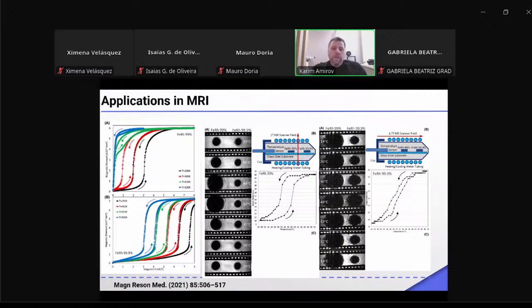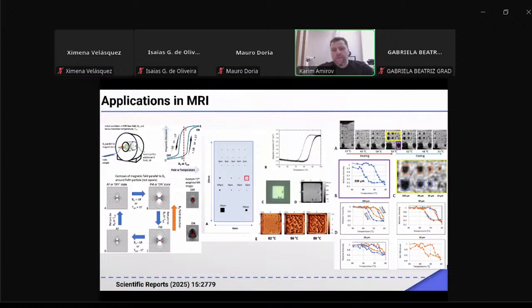This effect was shown in bulk. If it works in particles, it's very good news because you can construct special MRI labels with a switch-on mechanism. So what does it mean? It means when the human temperature is increased, the label works. You can see the change in the MRI signal from the particle. The colleagues continued this work, and they show that it also works at micro scale.